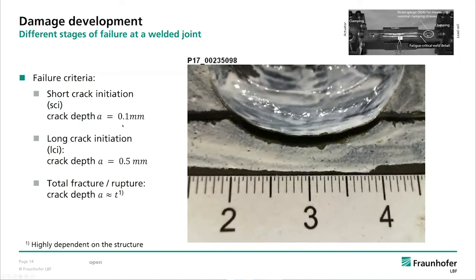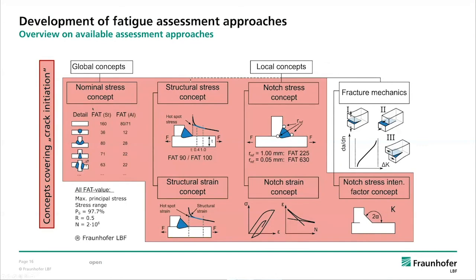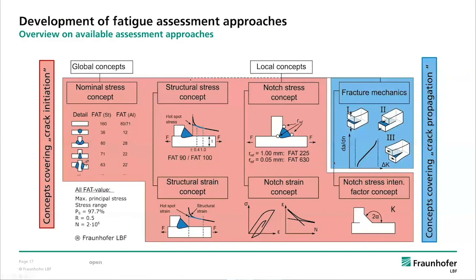So is it crack initiation we're dealing with? How long is the crack propagation phase? And this is important when we are talking about fatigue assessment approaches. So typically we have approaches for crack initiation: nominal stress, structural stress, notch stress approach. With these approaches, we can only assess crack initiation, not crack propagation, and then we have fracture mechanics. And so we really need to know what's up in the tests, and how this failure behavior can be correlated with a fatigue assessment approach.